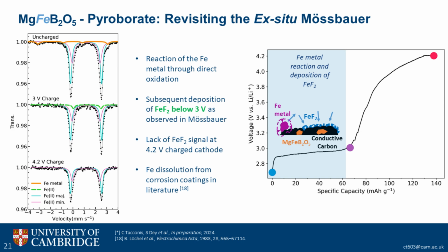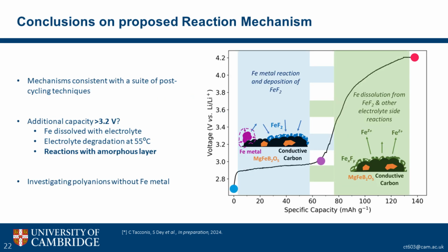What really is the source of this capacity at higher than 3.2 volts when we lose the plateau of the iron metal consumption? It could be a series of things. It could be the iron species dissolving into the electrolyte, undergoing further reactions. It could be electrolyte degradation, because the cell at this point has been sitting 50 or so hours at 55 degrees. And it could also be reactions with an amorphous coating layer of the polyanion system.